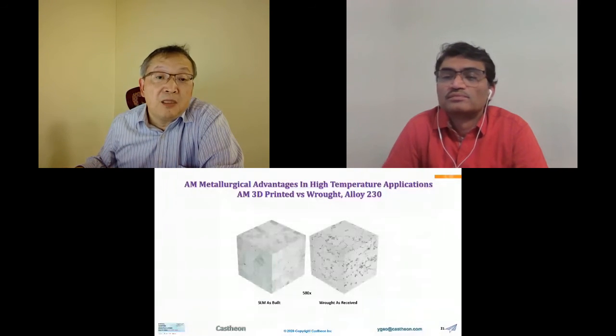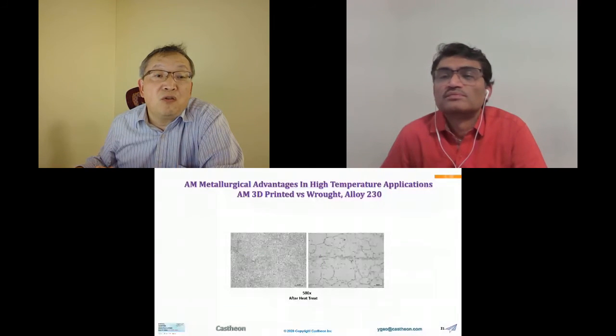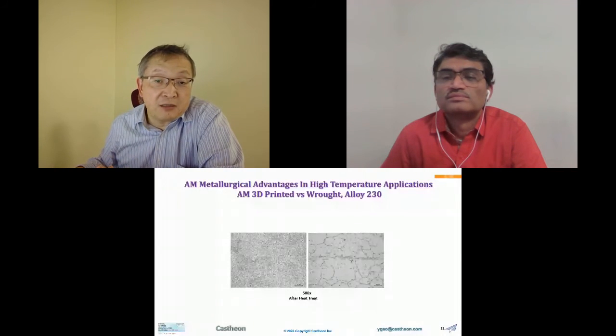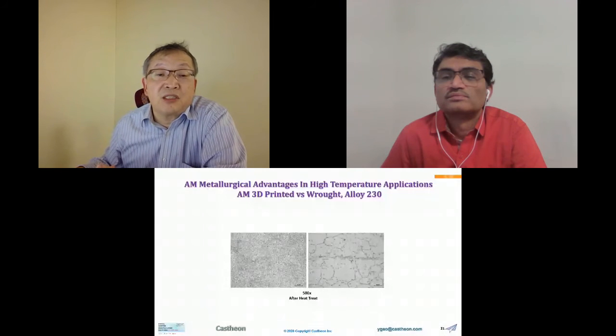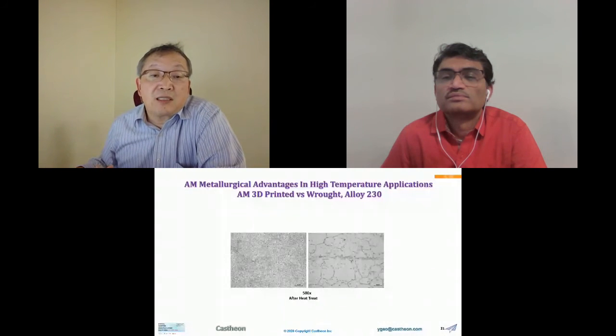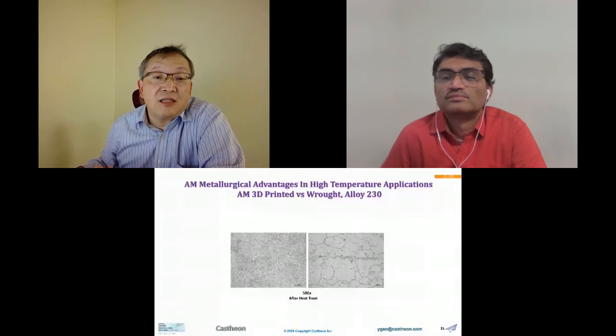Next, if you heat treat them, you can see uniform precipitation of the carbide. On the other hand, you have these large carbides already formed during the traditional mill process, the casting process. So you have to do an extensive thermomechanical reduction to get rid of those, because they lace the grain boundaries and cause sensitization of the material. So you basically lose the high temperature strength and you lose corrosion resistance.